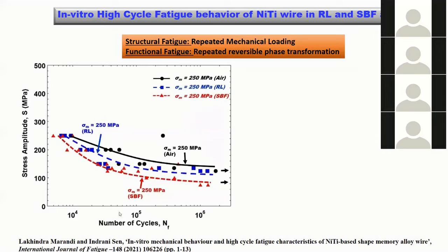curve, the stress amplitude versus the number of cycles it can survive. We have seen that for a number of cycles of around 10 to the power 6, the material in air can survive the highest amount of stress, which is around 140 MPa. And if we are testing the material in the presence of some kind of corrosive fluid, at human body temperature, we see that the fatigue strength is reducing. It is coming to 100 MPa only if we are doing the test in SBF.